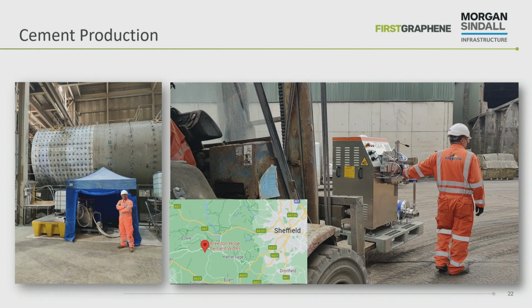Then we used our special mixer, just like we did at the lab scale. So we used this high pressure homogenizer. We set it up in that tent there. We had the IBCs, which had the graphene and the grinding aid, not well dispersed, passed it through that high pressure homogenizer to blast apart those graphitic particles into the graphene platelets, and that was dosed immediately onto the belt of the cement mill. So the grinding aid just goes on top of all the raw materials for the cement mill. And then at that point, it's business as usual.